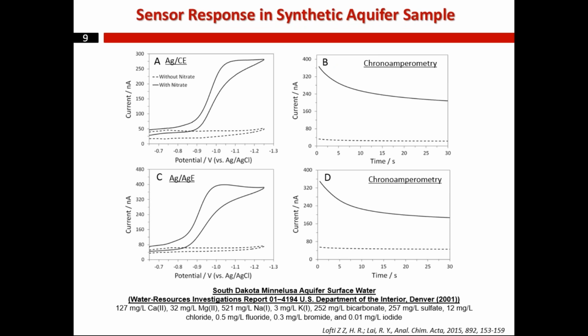Then we tried to see if the sensor can be used for detection of nitrate in the real world. So in this case, we made a synthetic aquifer sample based on what was reported from Water Resources Investigation Report from Department of the Interior, showing the main components of South Dakota's surface water. As you can see on these images, we basically saw that the sensor is selective enough for detection of concentration of nitrate in this complex medium. Therefore, we can say that these sensors can be used for detection of nitrate in the real world.